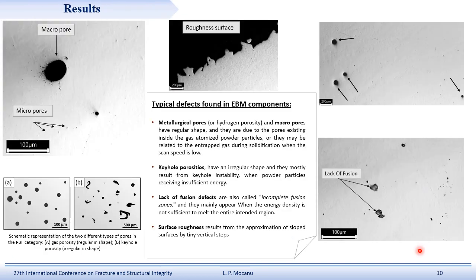So here are the results regarding the defects. We saw that both kinds of components are characterized by the typical defects in the electron beam melting process, which are mainly due to the process parameters, while the only defects which are due to the recycling process are all of this tiny porosity, which is due to the gas entrapped in the powders itself.